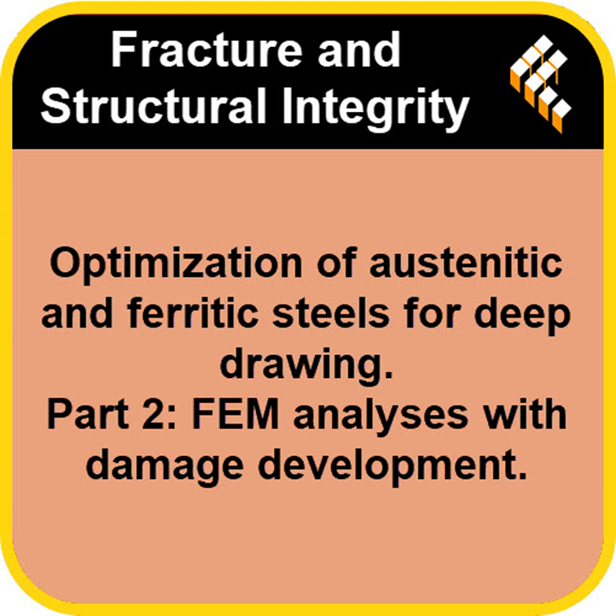But with the PVC film allowing flow, the thinning continues progressively right under the punch nose at the apex. The entire area deforms together much more uniformly right up until the material reaches its limit and cracks. That's the ideal homogeneous deformation. Which brings us neatly to the simulation side, the finite element modeling.